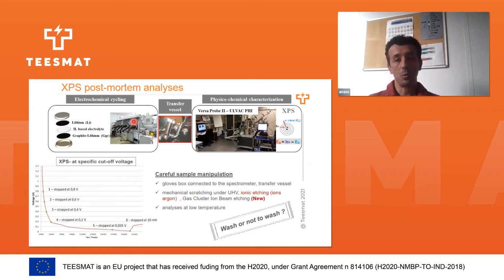Either we need, as I showed here, a glove box, or some laboratories connect the glove box directly to the XPS. It's not our case because we do not like this option. Or we can develop a transfer vessel that can help to transfer the sample from the glove box to the spectrometer. We can also make some pre-treatment by mechanical scratching, ionic etching, or other kinds of etching, or we can analyze the sample at low temperature, for example for liquid phases or polymers that are sensitive to the X-ray beam.